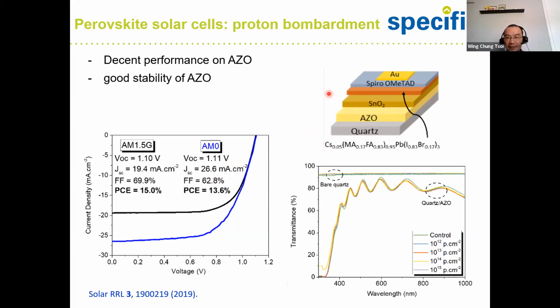So basically we make the solar cells, right? And then we measure the performance under AM 1.5G, which is more like the spectrum on Earth, and then under AM0, which is the light spectrum in space. Our study showed that if we use this so-called AZO transparent bottom electrode, we can make a pretty decent solar cell with good power conversion efficiency. Even for AM0, the efficiency is still pretty good for a single junction perovskite solar cell using this electrode.